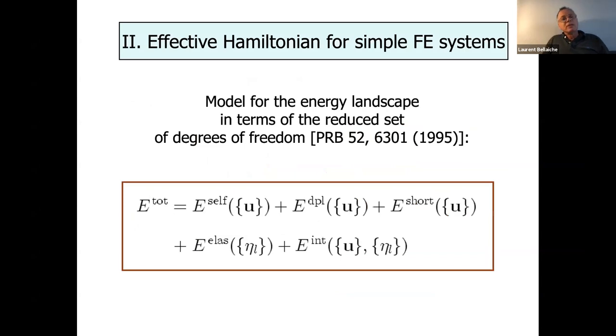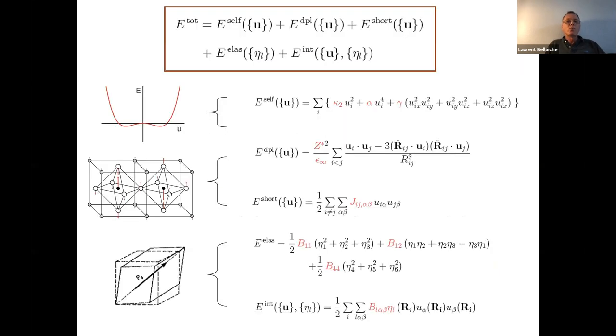So first, effective Hamiltonians were developed for simple ferroelectric systems. This is a very famous paper by Zhong, Vanderbilt, and Rabe. And there were five terms there, but dependent on local mode and strain. Let me go through them one by one. So you have the self energy. And the self energy is basically describing the double well potential. You have dipole-dipole interaction, very important for ferroelectrics, not so important for magnetic systems. You have short range interaction between dipoles. You have pure elastic energy that tells you how much it costs the system to deform, elastically speaking. And you have interaction between the soft mode, which means dipoles, and the strains.